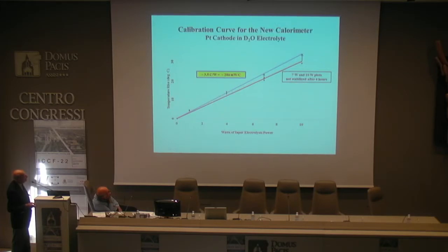So the calibration curve that we get, shown here, watts of input electrolysis power versus the temperature increase inside the cell, is not yet satisfactory because we have this uncertainty at the higher power levels. And it's almost certainly due to the changing electrolyte level at the higher power levels because we burn through the D2O faster, but we are verifying that in a run that's going on right now, and if necessary, we have a means of making an additional feed of the D2O in order to stabilize the electrolyte level.